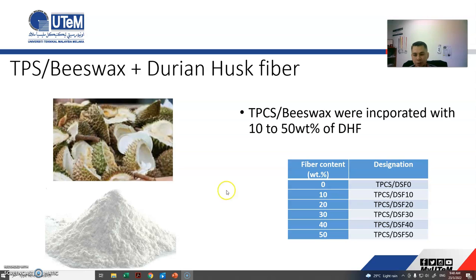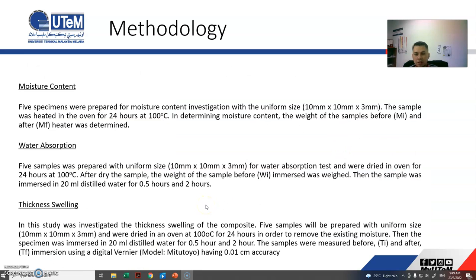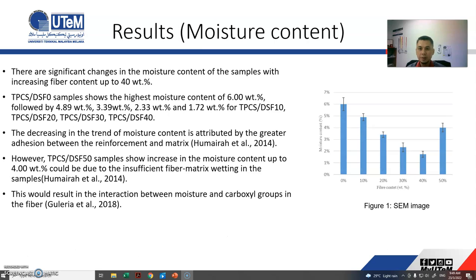So in this study we try to utilize the durian husk. There is some processing to make it into a fiber, such as rotating, grinding and sieving, and then this fiber was mixed with the starch from 0 to 50% of fiber content. Because we focus on the water absorption properties, we are presenting the results for the moisture content, the water absorption, and also the thickness swelling.